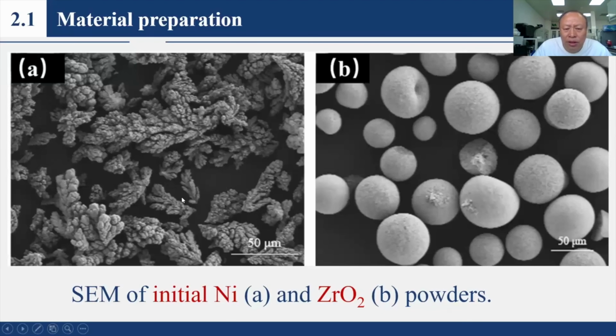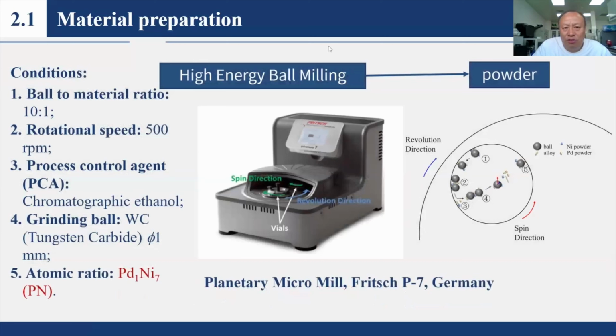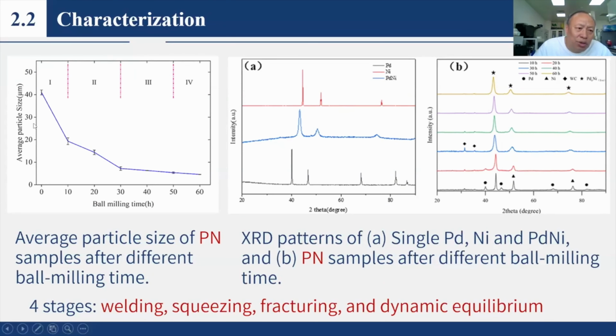And these are the initial nickel and initial zirconia powders. The grain size is about 50 micrometers. We use a high energy ball milling method. This is the micro mill, and these are the parameters during ball milling. Firstly, we report the palladium 1 nickel 7 powder. The left picture shows the particle size of palladium-nickel samples after different ball milling times, from 0 to 10 hours, 20 hours, 30 hours, and up to 60 hours.